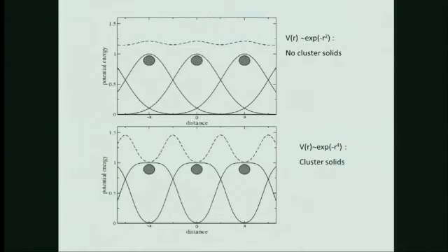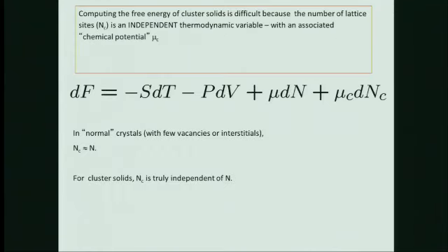This is the simple argument why they form. It's very hand-wavy. This is the potential, the repulsion of different particles. Now you say, where can I put the next particle? If it's a Gaussian potential, you put it where the potential is minimum. That's in between. If it's flatter than Gaussian, actually it turns out the minimum is exactly on top of another particle. That's a very rough argument that gives you a feeling for why you would ever get clustering. And it's easy to work out simple examples that show you the clustering actually should happen. Now what's the interesting thing? Normally when we talk about the crystal, we don't really distinguish carefully between the number of particles and the number of lattices.